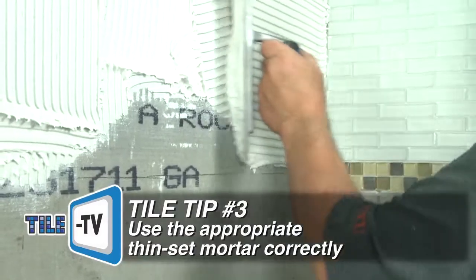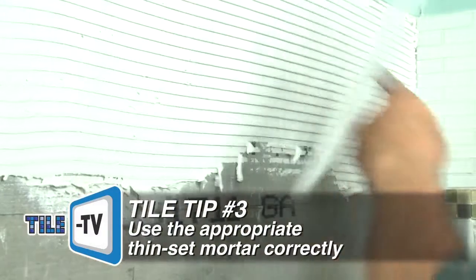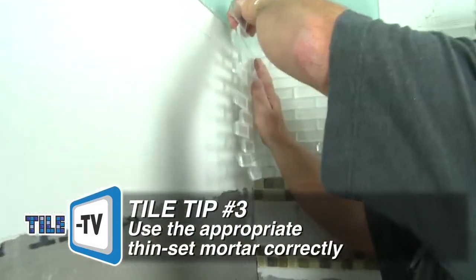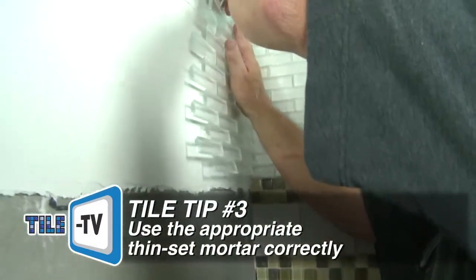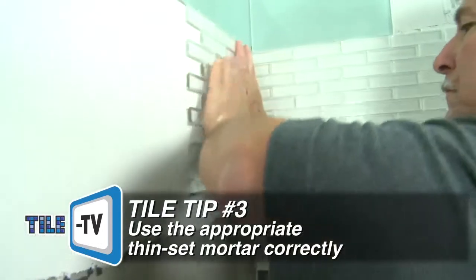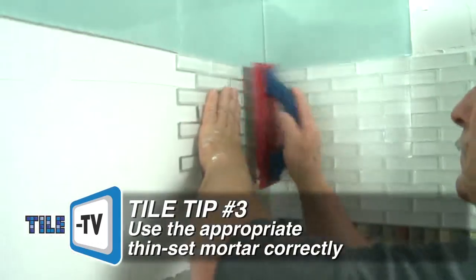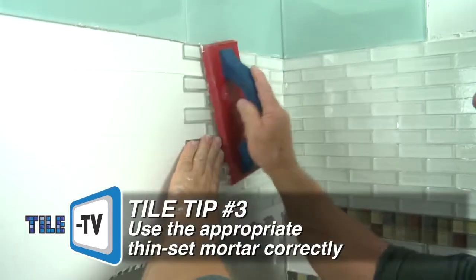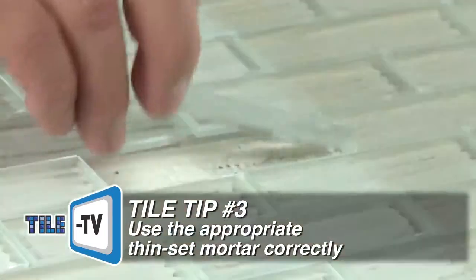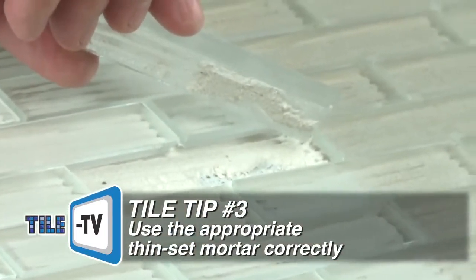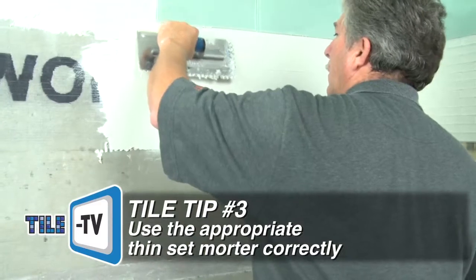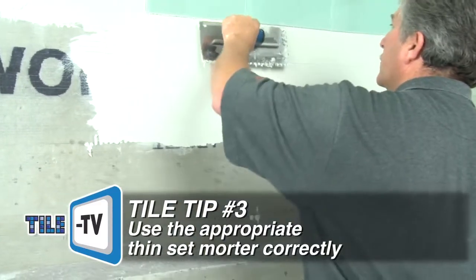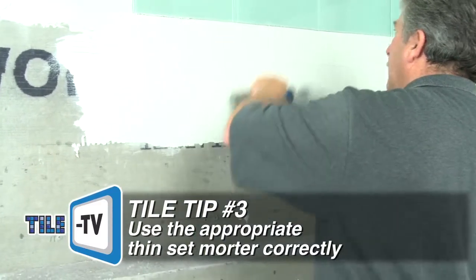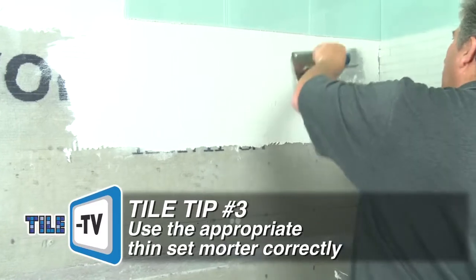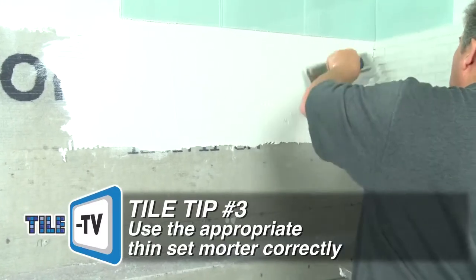In typical installations, a mortar is applied with a notch trowel and ridges, and tiles are pressed into the mortar in a back-and-forth method. While this may not be an issue for opaque glass tile, knock the ridges flat and back butter translucent or transparent tiles and eliminate those voids in the mortar. Glass Tile Premium Thin-Set Mortar was formulated for easy spreading to help in this process. It is also formulated to resist excessive shrinkage, which is critical with a smooth glass surface.